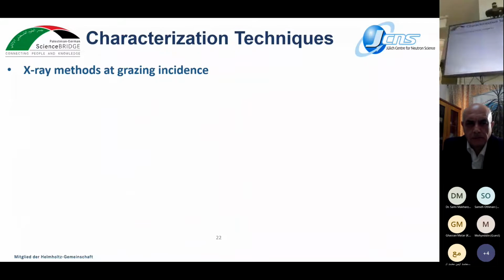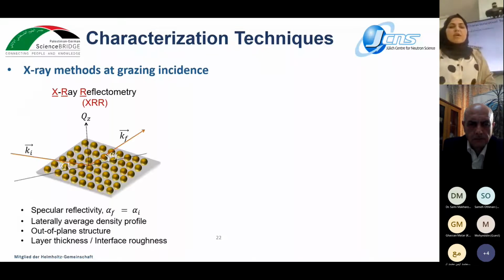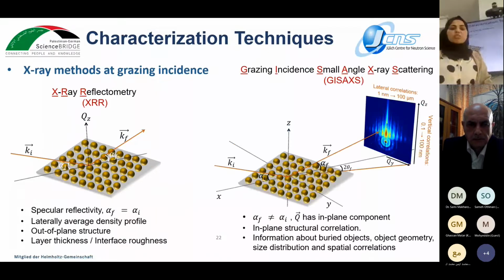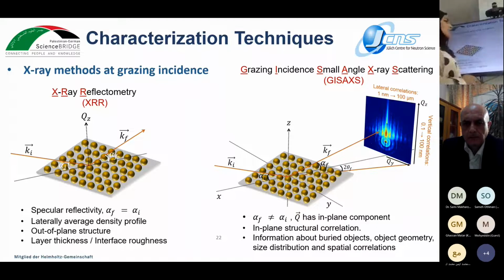Now, briefly, the main characterization techniques that I used during my study. First, I used X-ray methods at grazing incidence. Two measurements were performed, X-ray reflectometry and grazing incidence small angle X-ray scattering. Both were performed at GALAXI, which I'm going to present in the next slides. Both are surface-sensitive scattering techniques, which I use to characterize thin film, monolayer, and multilayer systems, and the setup of both is almost similar.